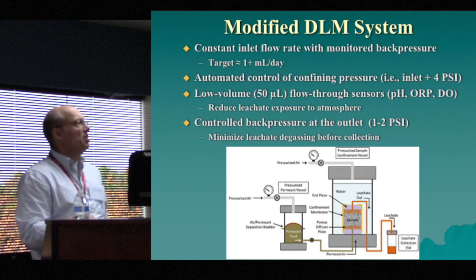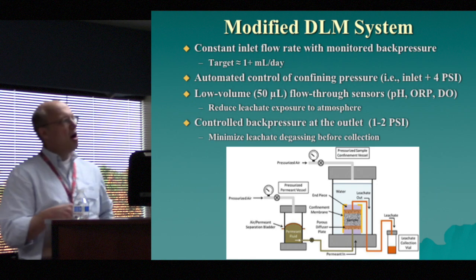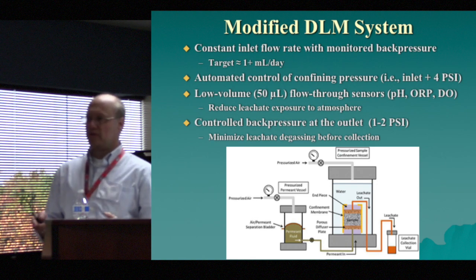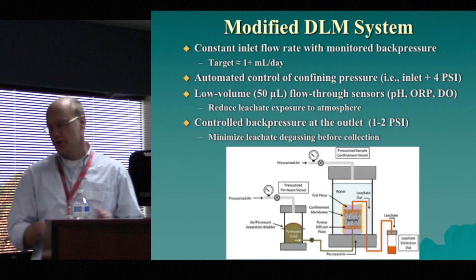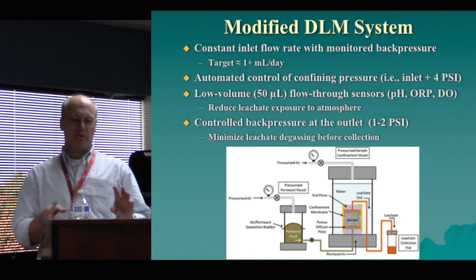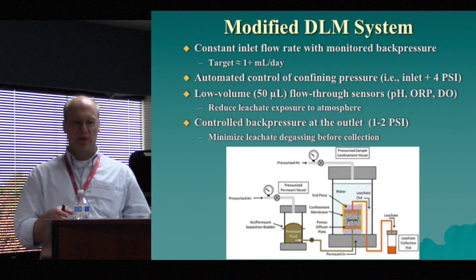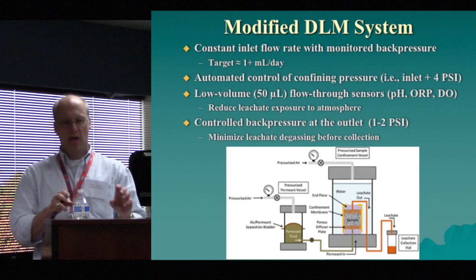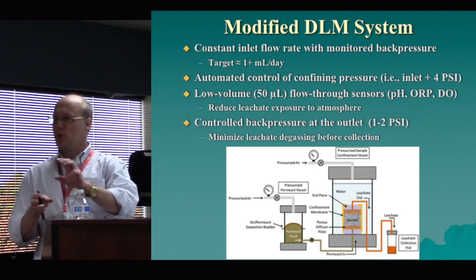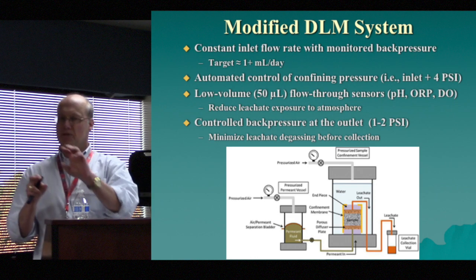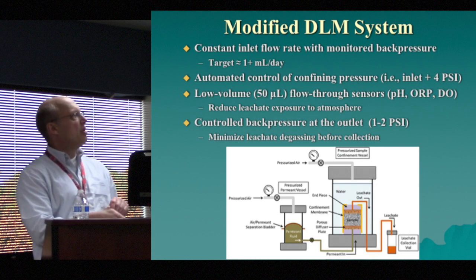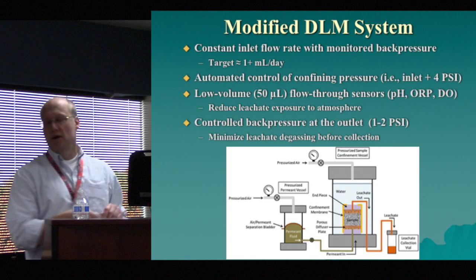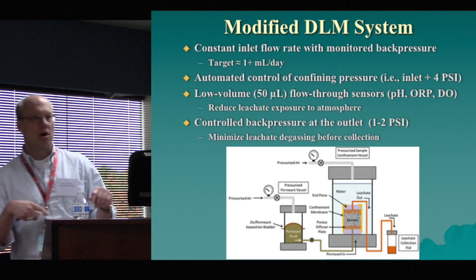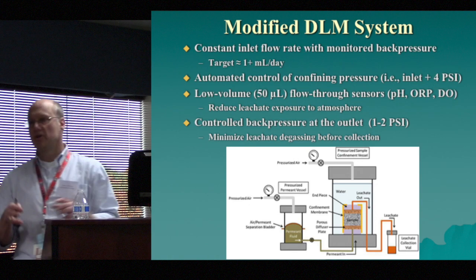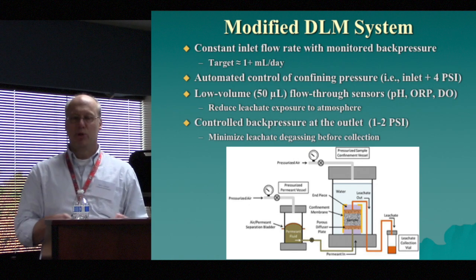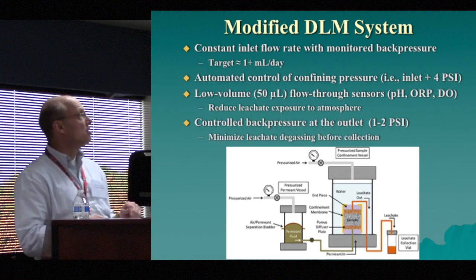We also have the ability with the new system to automate the control of the confining pressure. And what you really want to do, and what's very difficult with these kinds of samples that are changing over time, is adjust both of those pressures together, so that you're always about 4 psi higher on the confining pressure than you are on the inlet pressure, to make sure that the column doesn't blow up because of the inlet pressure.